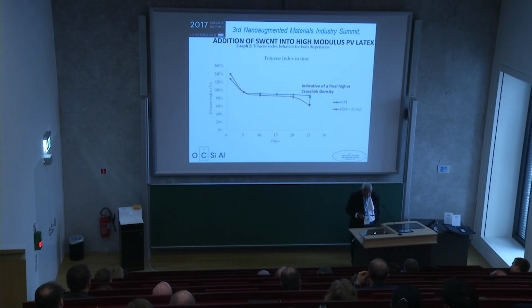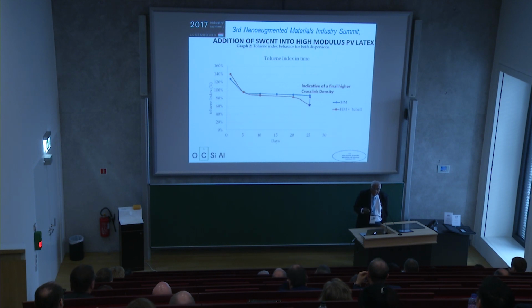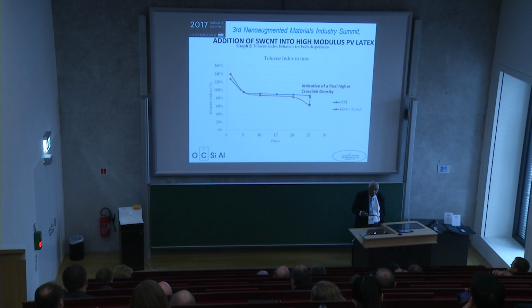So when we cure it, we do get a parallel curing. We measure the toluene swell index, and as the cure progresses within the molecule, the swelling of the particles reduces, and that swelling gives us an indication of the cross-linking that is taking place within the latex particles. And we find that when we did it with Tuball, we got a final kick with the Tuball, giving a slightly better cross-link density in this particular high modulus PV latex that we are working on. We have further improved on this. When we pass it through our pressure homogenizer, we get a much more significant improvement in the cross-link densities.